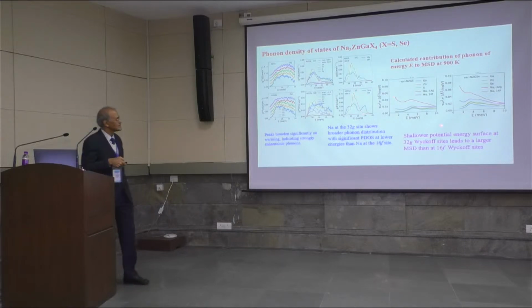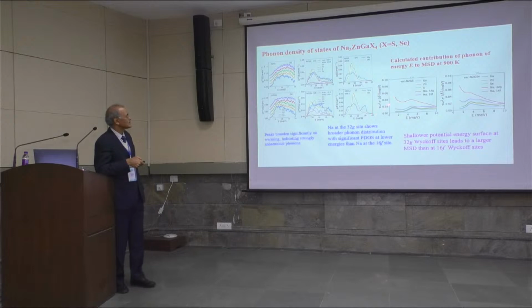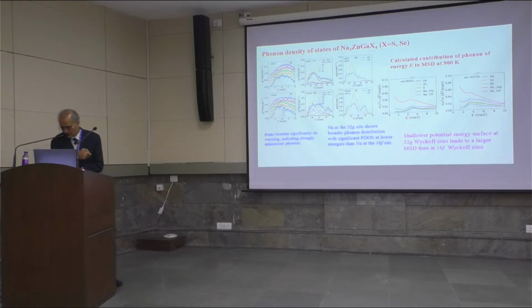And then these are calculations of the mean square displacements again, which tell us that the sodium of the 32G site has a large component at this low energy, where these low energy phonons are.